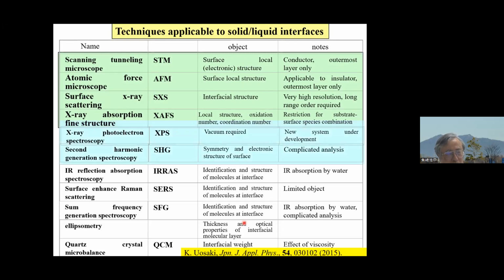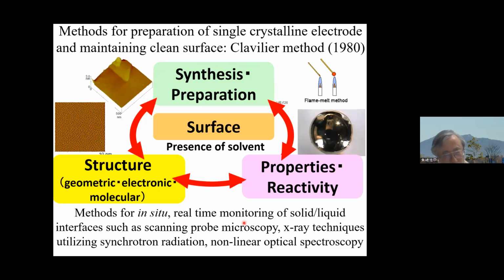The electronic structure is more difficult to determine. Electrochemical methods can be used, and second harmonic generation spectroscopy can be used, but both are relatively difficult, not straightforward. XPS is, of course, a vacuum technique, but recent development allowed its use by using a window separating vacuum and electrolyte. The molecular structure can be determined by vibration techniques such as IRAS, SERS, and sum frequency generation. In addition, sometimes you need information on the surface film thickness or the surface weight changes. We also contributed much to developing these techniques, and we also had access to radiation sources.